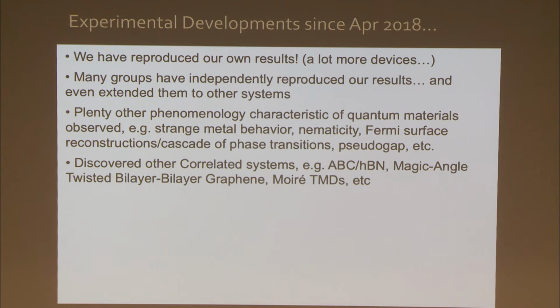We have discovered many other correlated systems using these twistronic platforms, or this Moiré quantum matter platform. They include ABC trilayer graphene aligned to HBN, and magic angle twisted bilayer graphene. We call this twisted bi-bi. It means 2 layers of graphene with 0 angle, another 2 layers with 0 angle, and now we twist them on top of each other with a magic angle. That's also a very interesting magnetic system. We have also transition metal dichalcogenides Moiré systems. There are really, by now, several dozens of these systems, which all exhibit very interesting characteristics in physics.